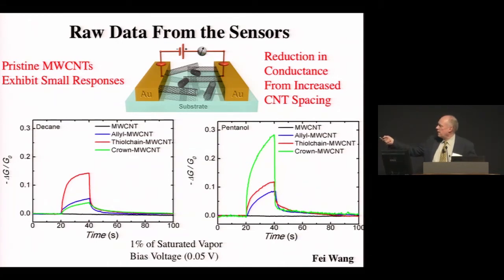So here again is that conductance change. Here's the one on the side that has the biggest response, the one that just has the pure hydrocarbons on the multi-wall nanotube, and it responds most, by a decade. So what's happening here is we took these multi-wall nanotubes, we took the outer wall and we just saturated it chemically, so it's an insulator. Think of it as insulation. It's like a sponge that absorbs it. So when it absorbs it, they tend to expand slightly. So what we are really doing is we have something that's purely a swelling mechanism that's changing the distance those electrons have to tunnel between the two tubes. And so naturally we get an increase in resistance between the nanotubes.